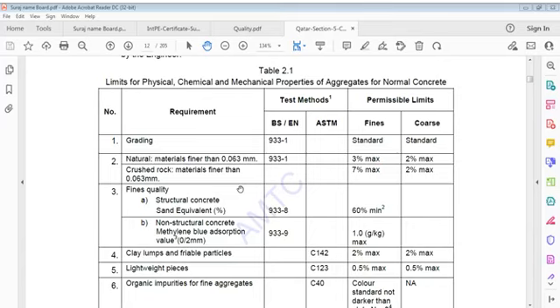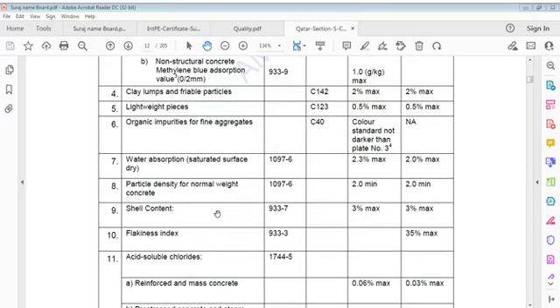So we can say clay lumps and friable particles. Clay lumps and friable particles, ASTM C142. The permissible limit is 2% maximum for fines and 2% maximum for coarse. Then the next is 0.5% maximum in fine and 0.5%.